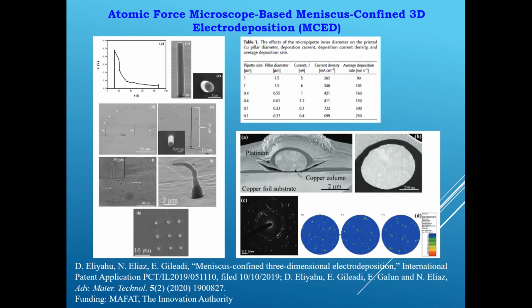Table 1 shows you the effect of the pipette size on the pillar diameter, the current density, and the average deposition rates. Note that the highest deposition rate of 300 nanometers per second in this case is already comparable to common deposition rates in industry. The bottom right image is just to show you some of the material characterization that we did. So we saw that there was no preferred orientation in the Z direction.